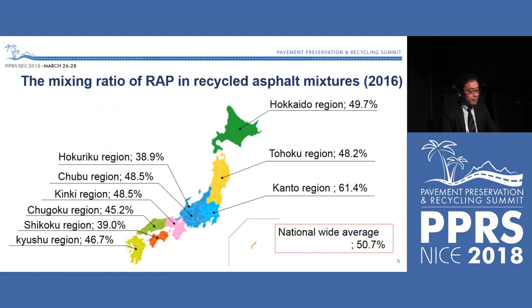What you see here is the mixing ratio of RAP in recycled asphalt mixture in 2016. The ratio is different among the areas. The ratio is the smallest in the Hokuriku region. It's 38.9%. Nationwide average is 50.7%. The ratio is the largest in the Kanto region. It's 61.4%.